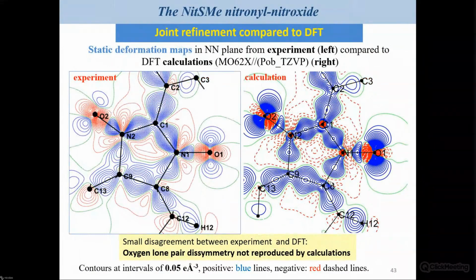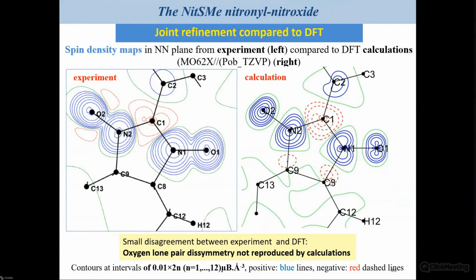But if you now compare what happened specifically on the nitroxide function, you observe that again, you have a dissymmetry for the experimental part, which is not reproduced in the DFT calculation. So that is maybe a limitation of that kind of calculation, which is not sensitive enough to those very, very tiny aspects of the interaction in that kind of materials. We also have the same conclusion if you look at the spin population on that